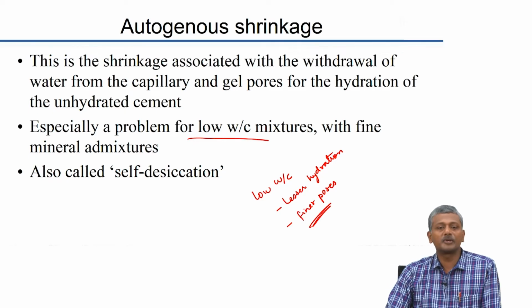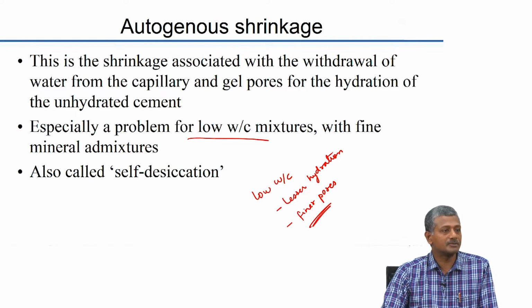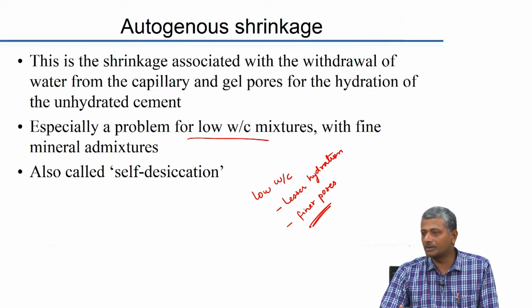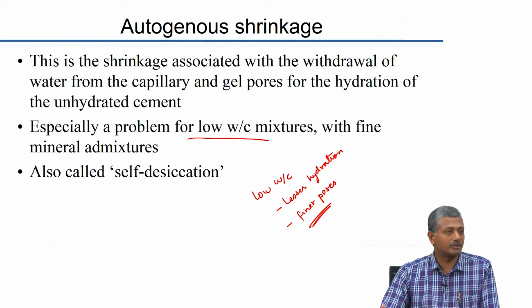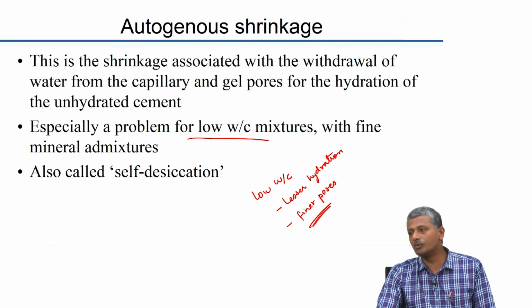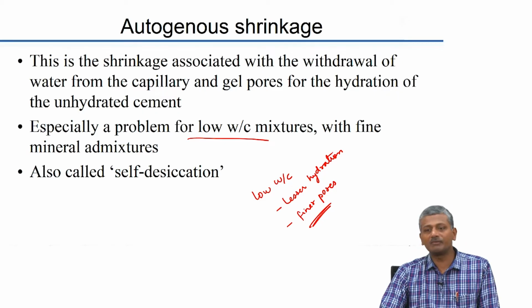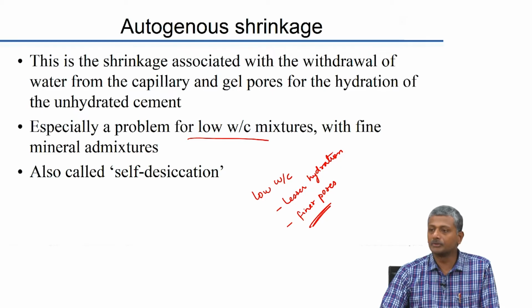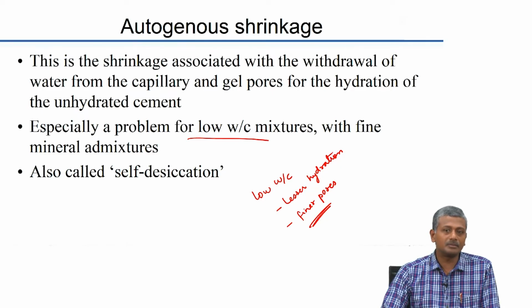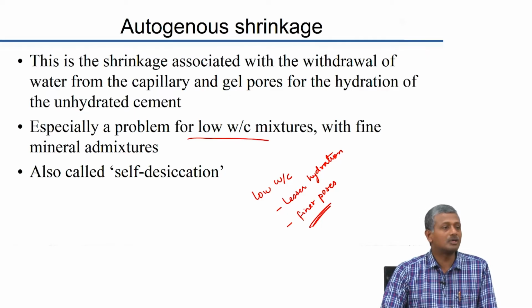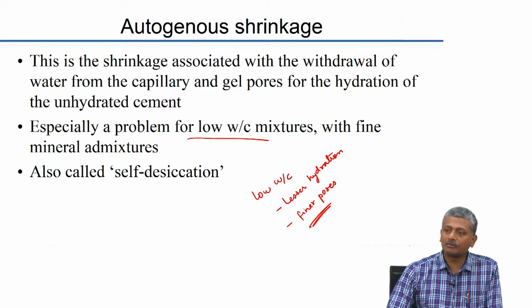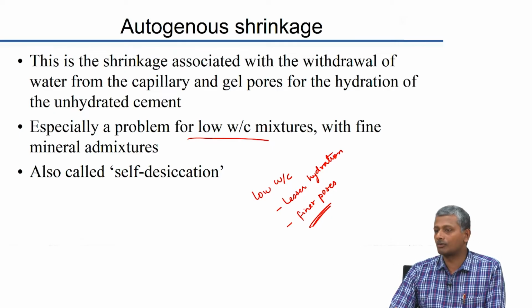Why should drying shrinkage be low in low water cement ratio systems? There is no water to evaporate out of the concrete. There is very little water that can actually go out of the concrete. Okay? So, what is actually happening is the water is moving within the concrete only. So, that is why we call it an autogenous shrinkage. So, this concept of autogenous shrinkage is something that people are not yet fully confident of handling as far as the design of concrete and curing, subsequent curing of concrete is concerned.